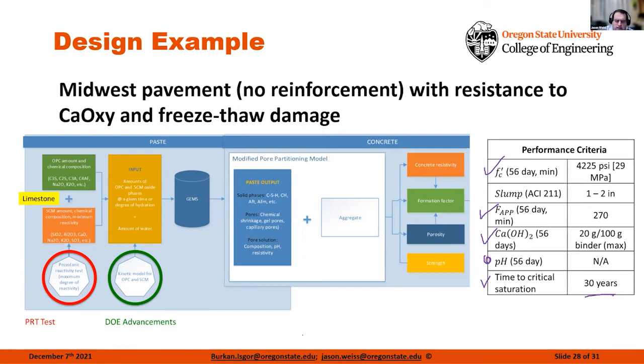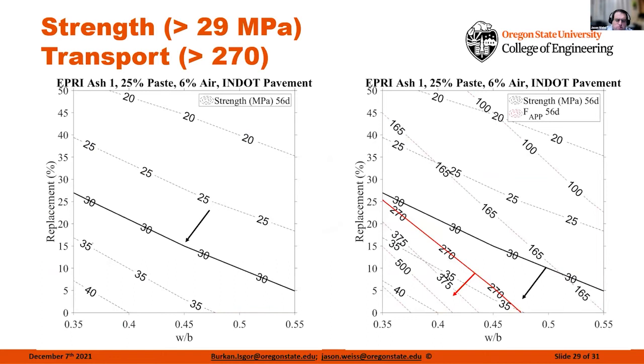So I have a certain SCM available, I have a certain cement available. I can start to go through and I can make these concretes. And what I can start to do is make these sorts of plots. So the idea here is I can say I've got water to cement ratio along my x-axis, water to binder ratio. I've got the amount of SCM along the y-axis, and each one of these contour lines is a specific property. 20 MPa strength, 25 MPa, 30 MPa. So if my criteria is 30 megapascals, everything below this line is a feasible concrete for me to be manufacturing.